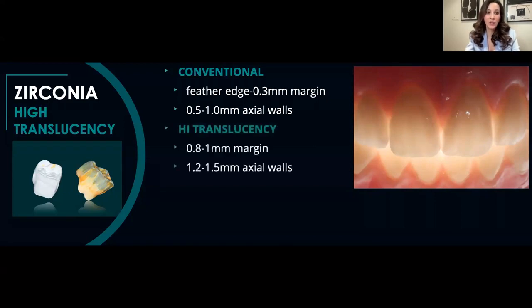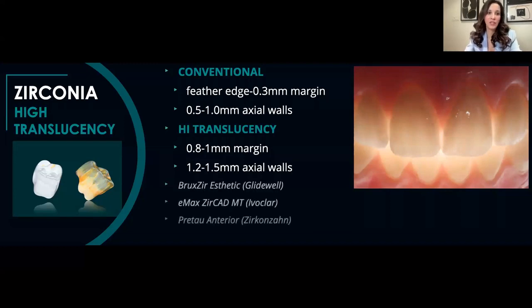Conversely, for your high translucency or your 5Y-TZP, you need a 0.8 to 1 millimeter margin and 1.2 to 1.5 millimeter axial wall reduction. So that mimics more of the particle-filled glass classification of our ceramic material. And some examples of this high translucency or 5Y material are listed up on the screen: BruxZir Esthetic, eMax ZirCAD MT, Pretau Anterior.